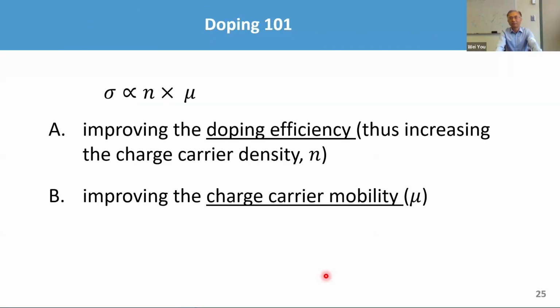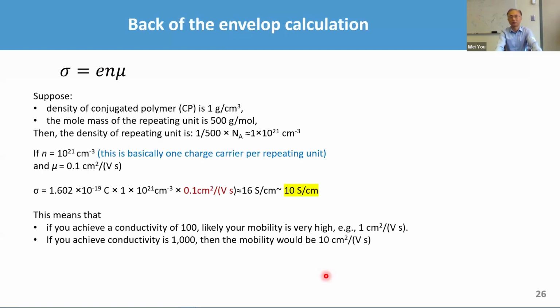Okay. Before we talk about the conductivity, remember back in the days that the resin polyacetylene got people excited because you can make it into a conducting polymer. Polyacetylene itself is a semiconducting polymer. It has very good mobility, but it doesn't have enough carrier density. Because if you try to make a conducting polymer conductive, you are essentially limited by the charge carrier density and also the charge carrier mobility. You want both numbers to be as high as you can if you want to get a really high conductivity. But you also have a limitation, which I'm showing on the next slide.